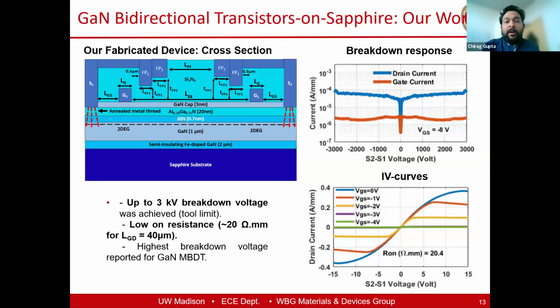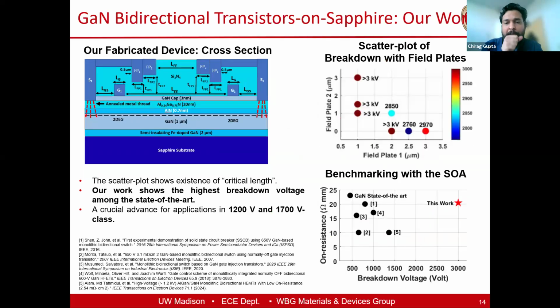So right now the on resistance that we got was 20 ohm millimeter, which was pretty good. And if we translate this number, it turns out to be close to 10 to 12 milliohm centimeter square, depending on how we account for active area in these devices.